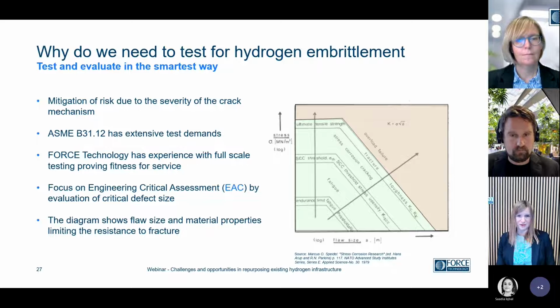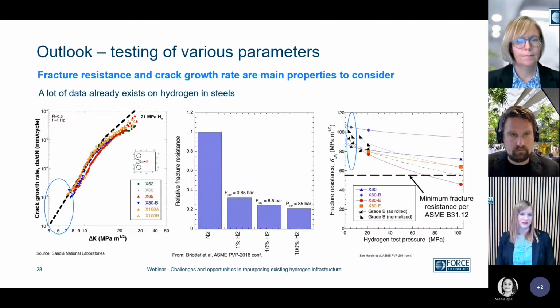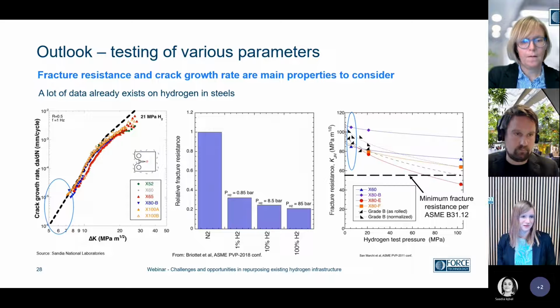So we believe that is the way to move forward, because we do have a lot of data already on materials in hydrogen environment for pipeline steels. Again, the risk is the uncertainty of the defect level. Here we have the ASME B31.12 master curve and X52 through to X100 pipeline steels, again showing quite similar behavior. And worth noting that at low delta K levels, we don't have the effect of hydrogen at all.